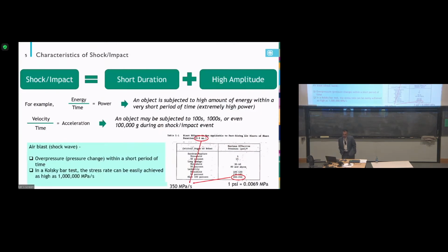So here, shock and impact. How can we express shock or impact? Basically, consider two factors. One is duration, a very short duration, plus very high amplitude. Now, high amplitude of what? That really depends. If we apply a very high amplitude of energy over a very short period of time, that gives you very high power. Or if you apply a very high amplitude of velocity over a short period of time, what's that? That's acceleration, something very high, we call it high G acceleration. It could be like 100,000 G during the shock or impact environment.